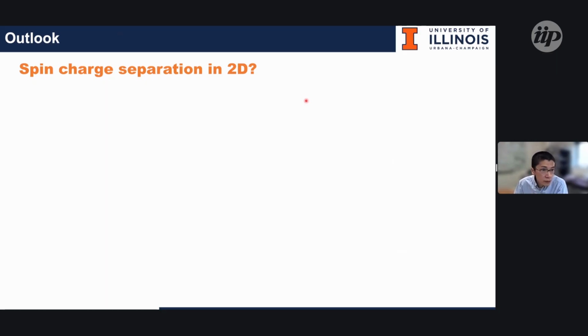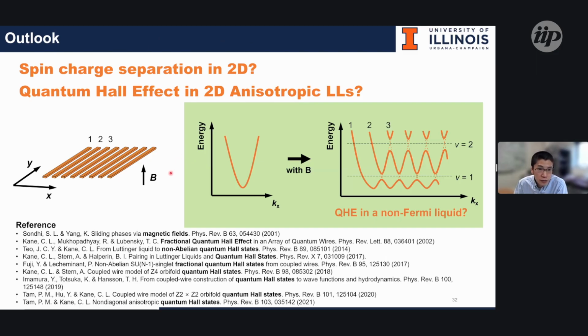Another possibility we can explore in such a system is to go up to very high magnetic field, where you can see the quasi-1D structures here. If you apply a magnetic field, effectively we can shift the band structure along momentum space. Then, if you can somehow create interaction between the bands, you can open up a gap, and in this way you might create a Landau level in a non-Fermi liquid. There have been numbers of theoretical proposals, but it hasn't been realized experimentally.